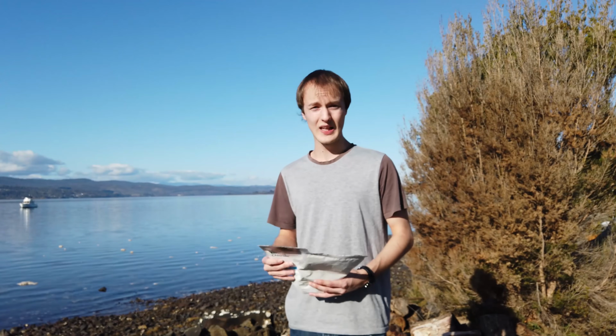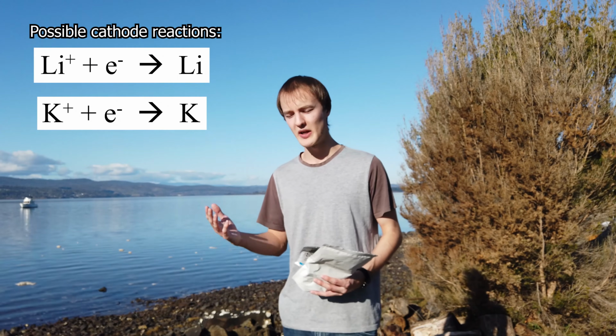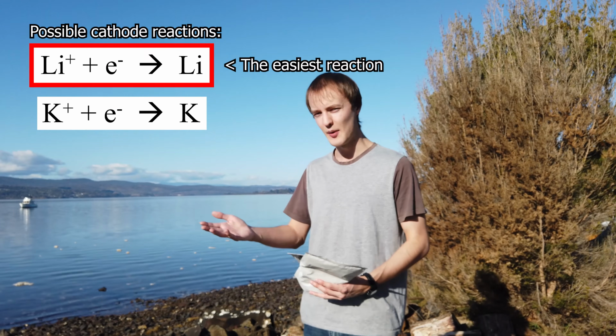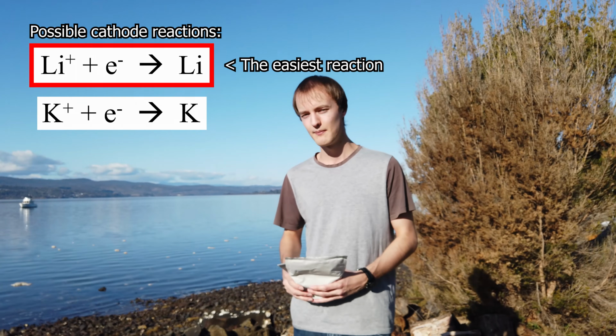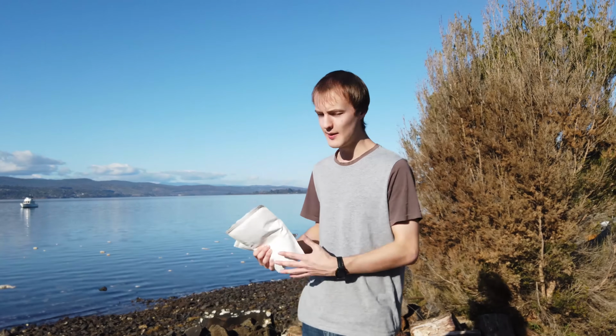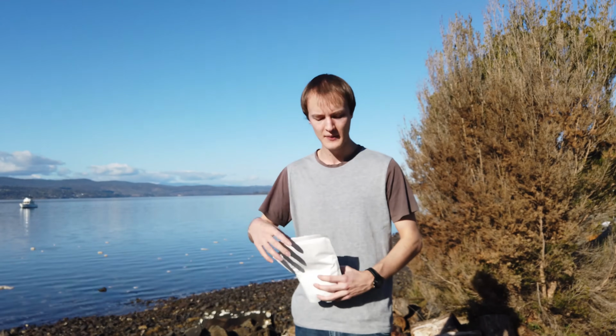And even better, when we electrolyse that mixture, we still get lithium metal because at those temperatures, it's easier to reduce lithium ions than it is to reduce potassium ions. As I said, that's what they do in industry to make lithium metal, and we've got no reason to do it any other way. To actually melt down our eutectic mixture, I'm going to be using a stainless steel measuring cup as the crucible. It's not the best idea to melt down chloride salts in stainless steel, but it's what I've got and it should last long enough to do a couple of experiments for generating lithium metal. So that's what I'm going to do. And with that, I think that's everything, so let's get started.